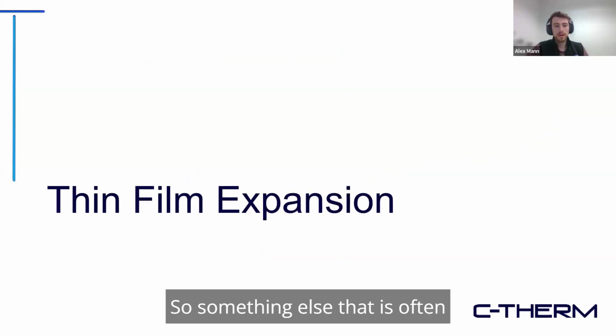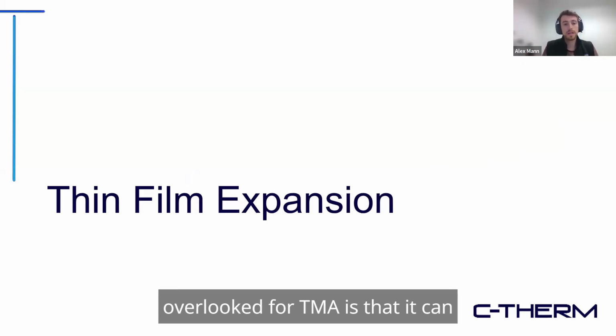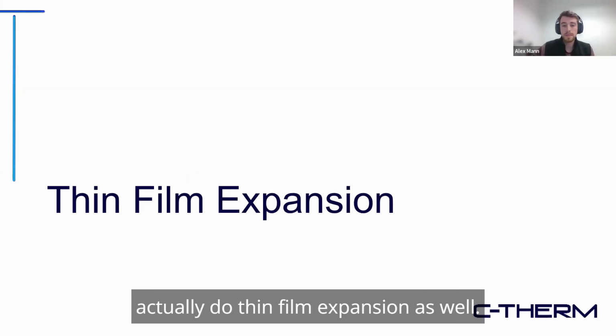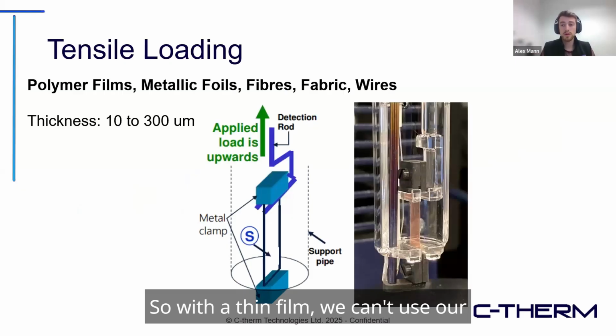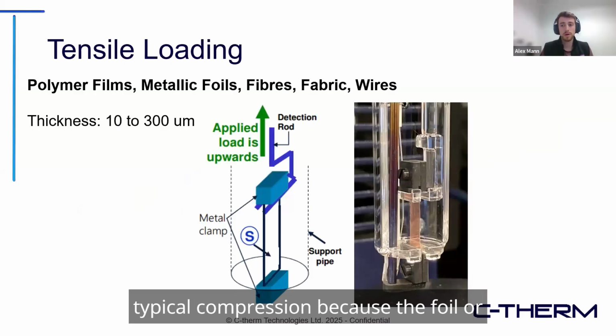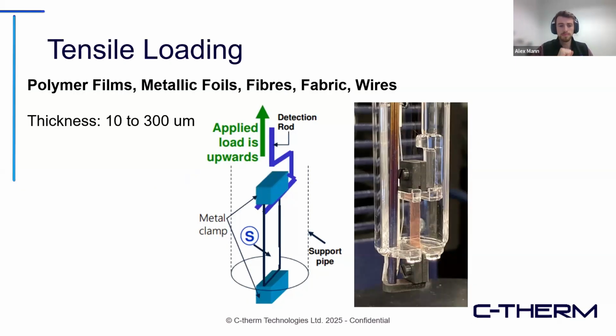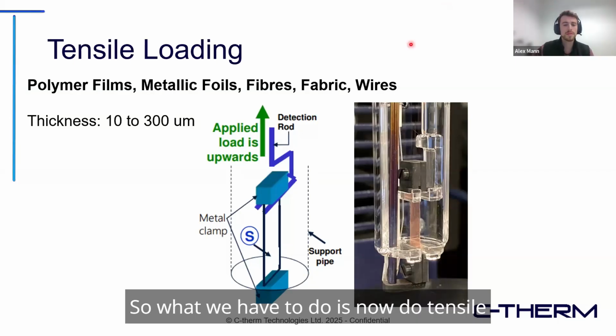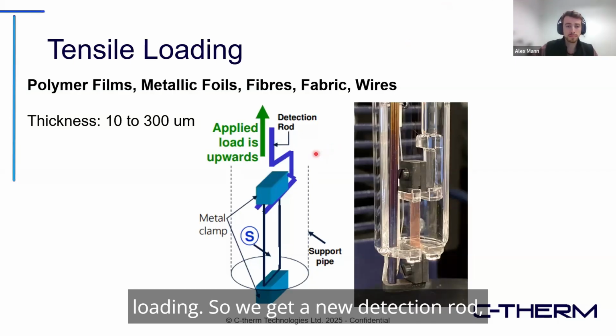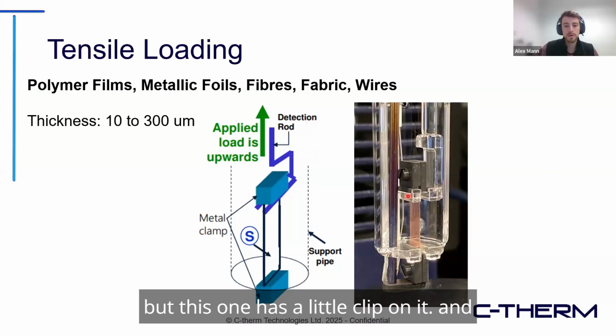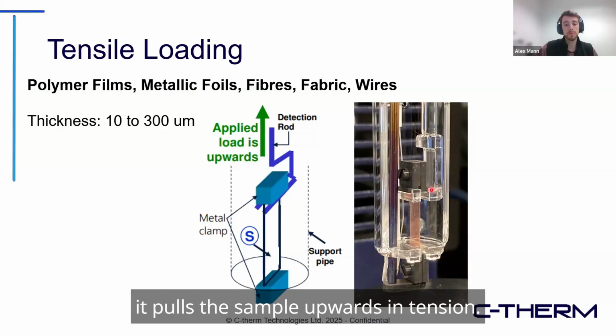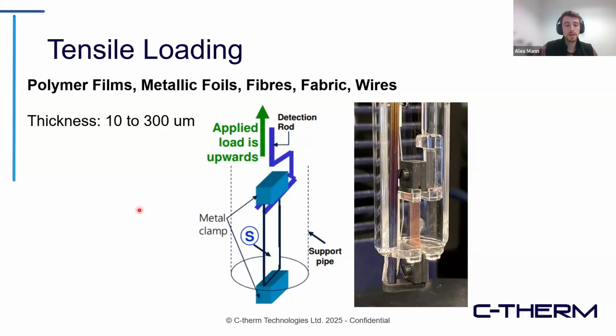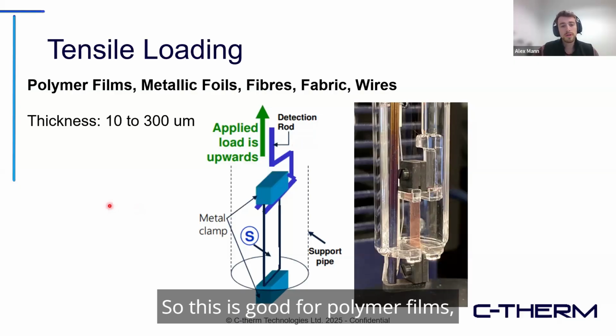So something else that is often overlooked for TMA is that it can actually do thin film expansion as well. With a thin film, we can't use our typical compression because the foil or film is going to buckle. So what we have to do is now do tensile loading. We get a new detection rod, but this one has a little clip on it, and it pulls the sample upwards in tension. So this is good for polymer films, metallic foils, fibers, fabrics, wires.